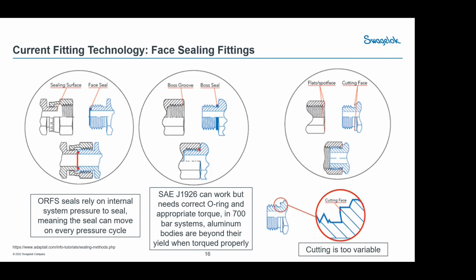The heavy duty has more thread. That gives us more thread engagement and allows it to have better strength under the body. The other problem is if this goes into an aluminum body, it gets very close to the yield strength of the aluminum. So what can happen is the combination of the load onto the shoulder and the pressure from the body can cause the threads to stretch. So great care needs to be taken on that aspect.